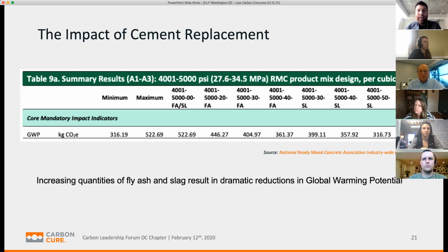What you're seeing as you go down the list, those numbers go down. And as you're seeing on the labels, the next one says 4001-5000-20-FA. That means that this mix has 20% fly ash replacement of cement. And you can see that that one has something in the order of 60, 70 kilograms less CO2. So again, that's just showing you that the more cement replacement you make, the greater the reduction in CO2 on average. And that points to the fact that cement really is such a defining factor here, that you can change 20% of the content and get a 60, 70 kilogram reduction in CO2.